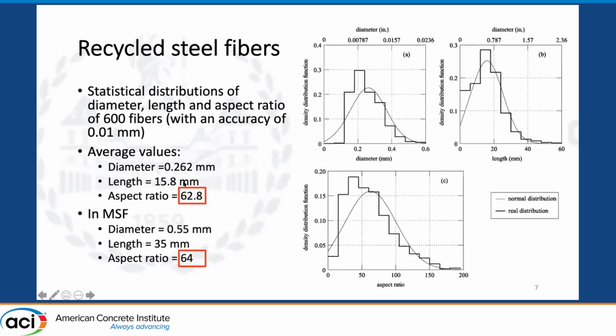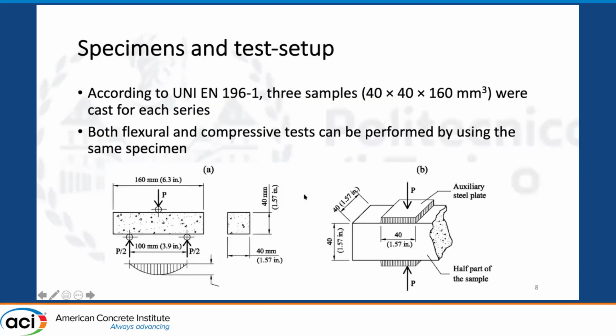and the average value are reported here. We also computed for these fibers the aspect ratio, which is 62.8, and in the reference composite, we used a manufactured steel fiber which has more or less the same aspect ratio. So, according to the standards for testing cements, we cast 3 samples for each composite, and